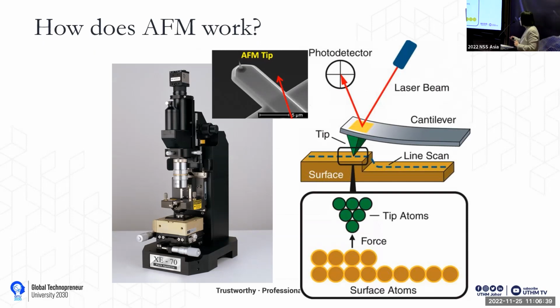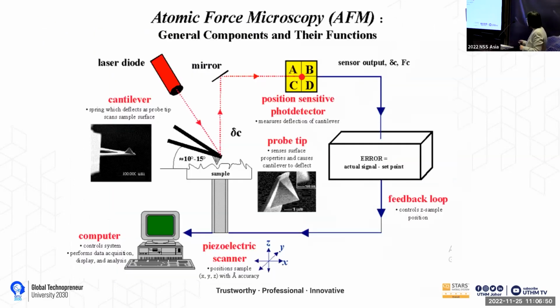So we actually measure the repulsive and attractive forces between the tip and the sample. That will give you the reconstruction of the topography. Okay, so it's actually more than that. It involves a very high speed feedback loop system to continuously monitor the scan rate and also the tip surface distance. So it has to be very high speed so that your scan, what I call the cantilever, will not collide with the sample, but will adjust to the topography of the sample.